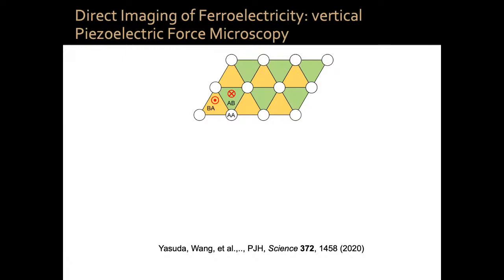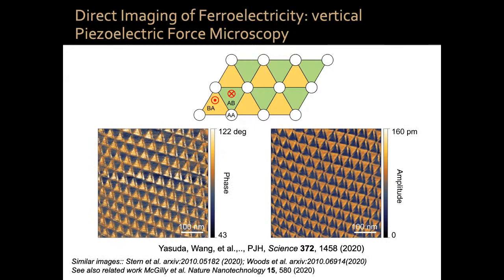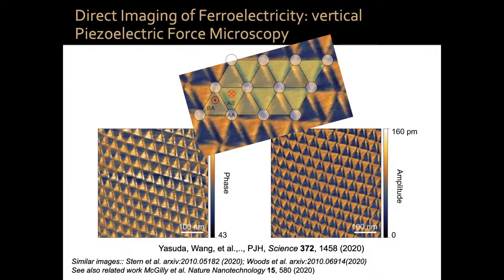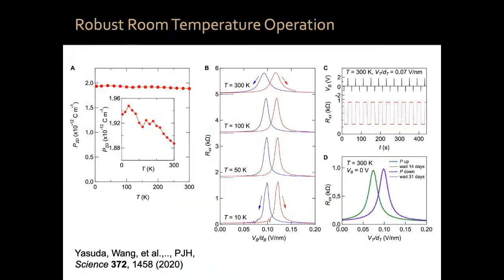It turns out there is a technique that allows you to see this. It's called piezoelectric force microscopy. And when you image one of these twisted devices, you can see this. This is the amplitude, this is the phase, this is telling you the opposite electric field of these AB and BA domains. You can put this on top of this, and you can see that it matches exactly. Not only that, this thing works at room temperature.